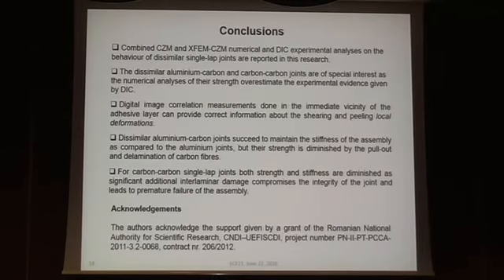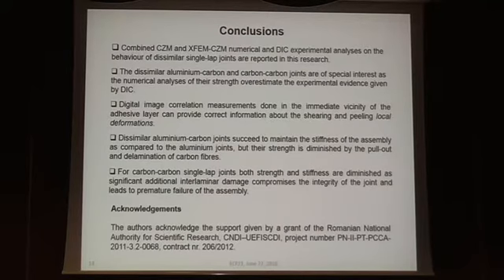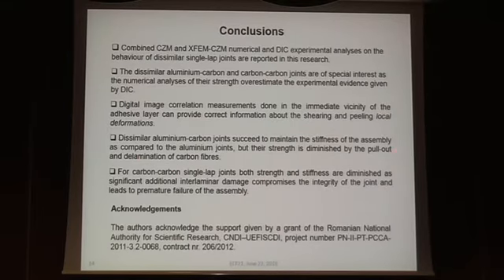As conclusions, we wanted to concentrate on dissimilar aluminum-carbon joints and carbon-carbon joints. Experimental evidence showed that it is very important to look at local shearing and peeling deformations. For carbon-carbon single-lap joints, we have both strength and stiffness diminished due to additional internal damage which compromises the integrity. We acknowledge the support of the project. Thank you for your attention.